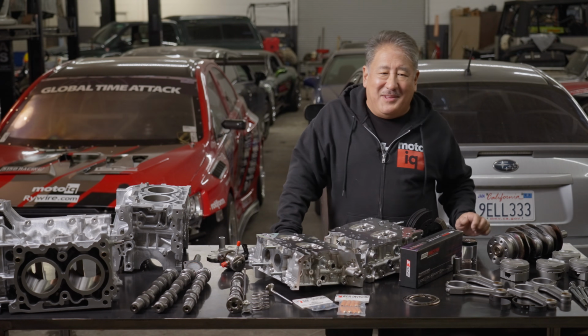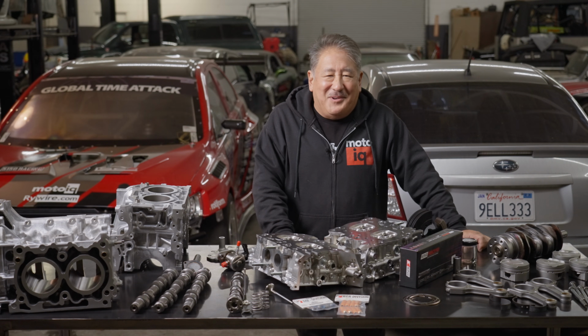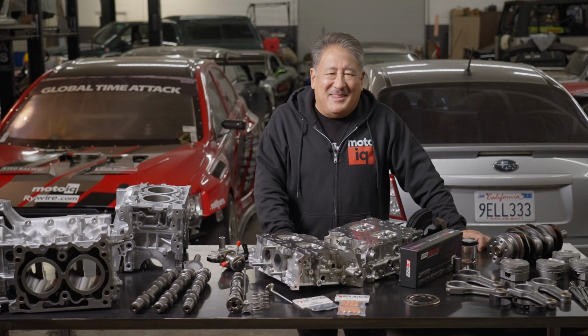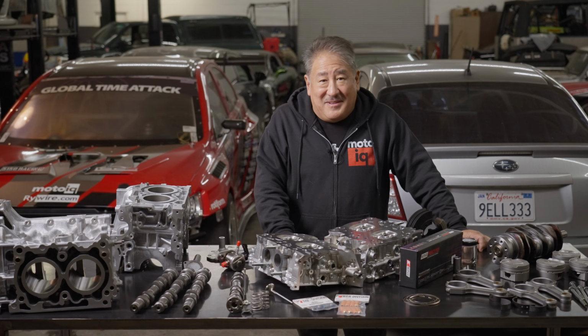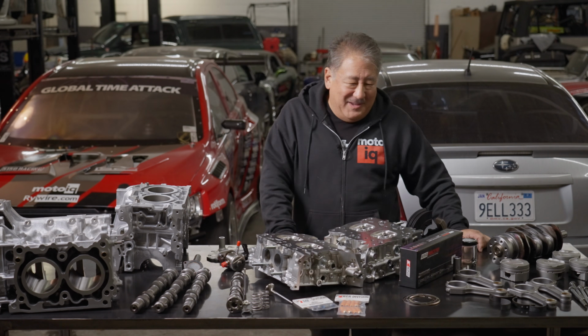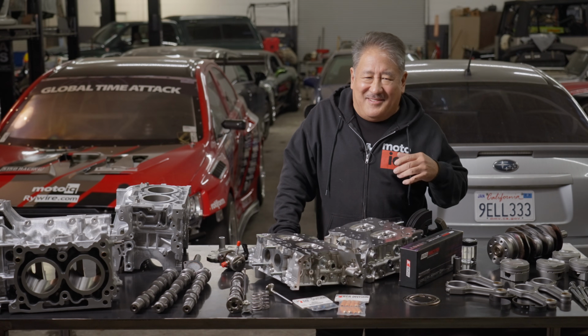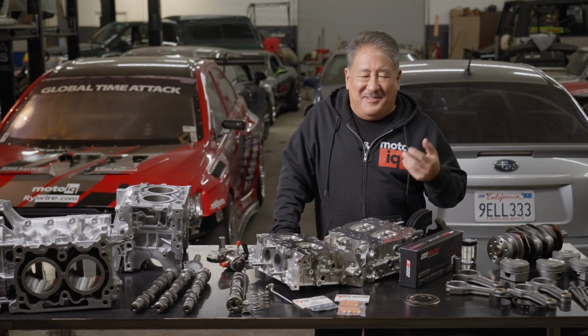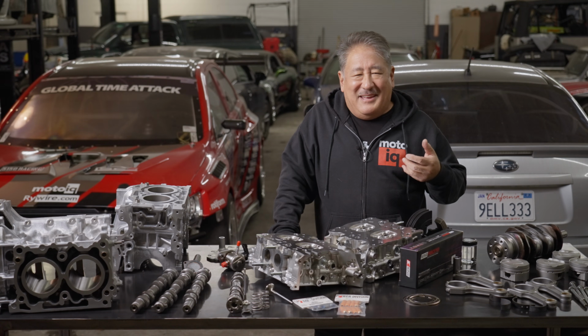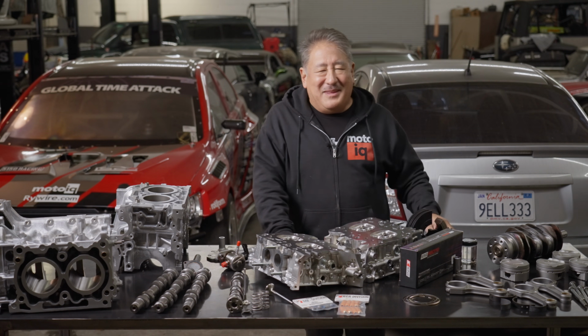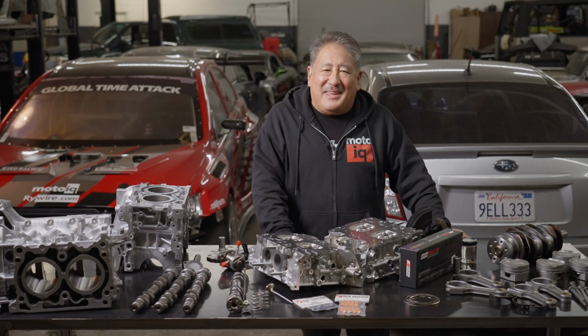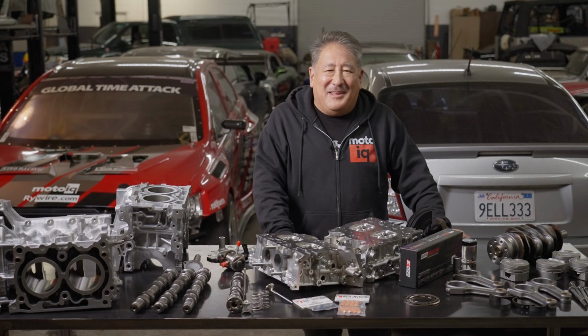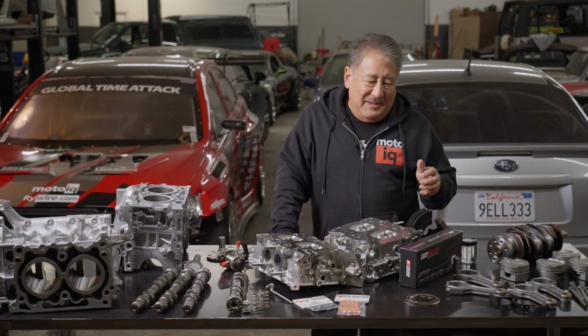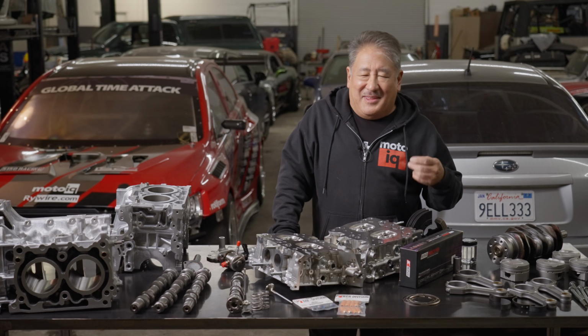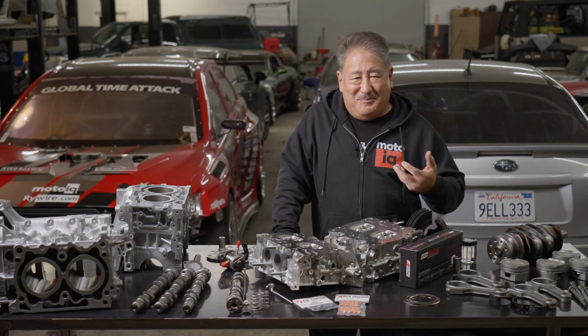The bearings are coated with a polymer coating, so it's not Teflon, but kind of like a Teflon, and it has molybdenum and slippery stuff in it. It also has copper nanoparticles. Now, traditionally, the top coating is a quick zinc plate, which is soft, helps embeddability, and helps the bearing burnish in when you're breaking it in. But it really can't take much load, and it doesn't really help the bearing's load capacity. But the XPC coating, especially with the copper nanoparticles, actually can bear load.